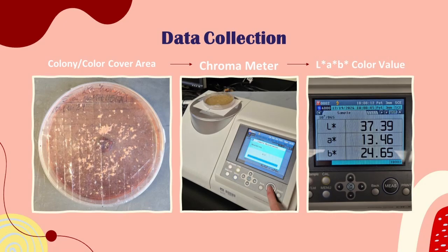The three best performing media types were then brought on to part two, where they were inoculated with white rotted wood. This allows the fungi to colonize their native substrate. Once these had grown for 10 weeks, they were dried, the plates ground up, and the pigment extracted. This is our final product. And from there, we can examine how best these media types produce pigments.